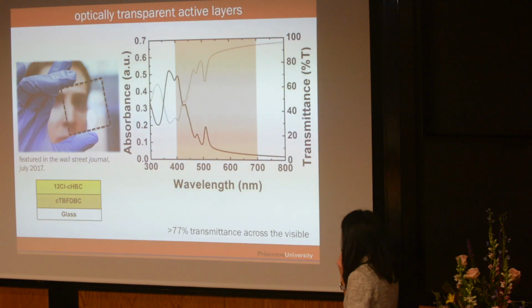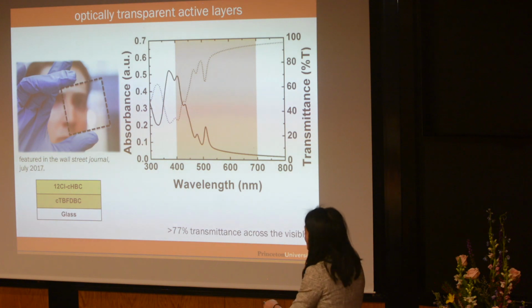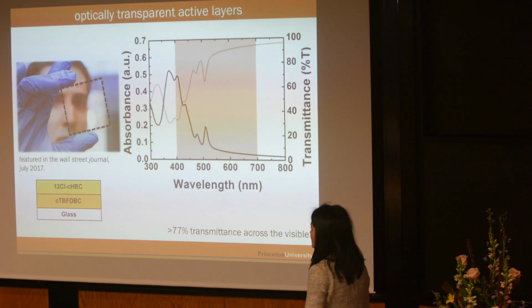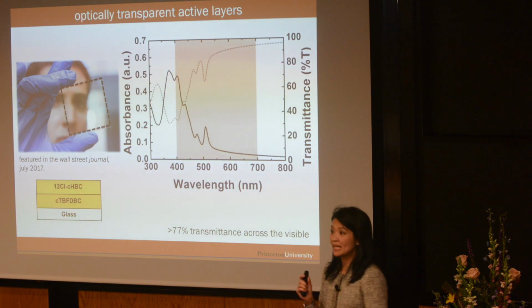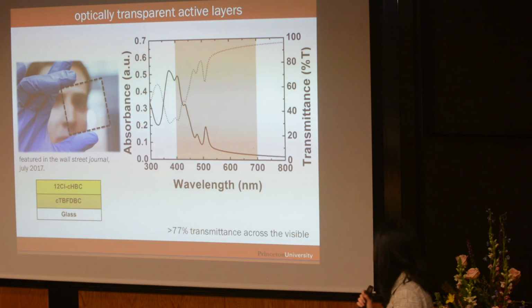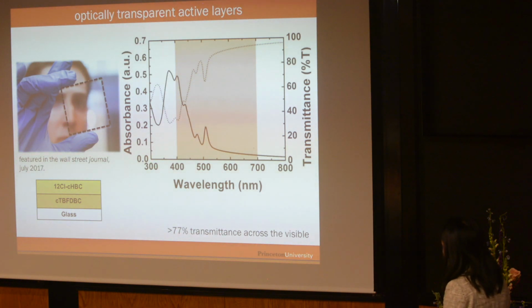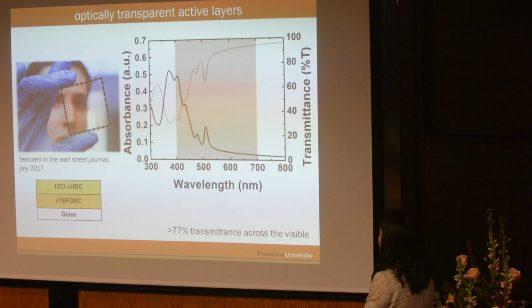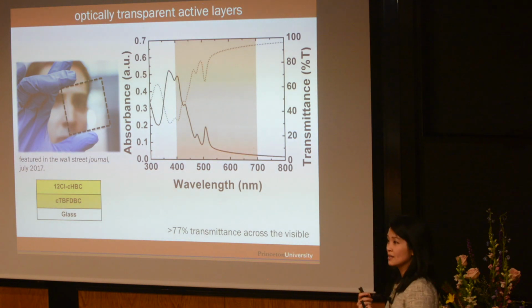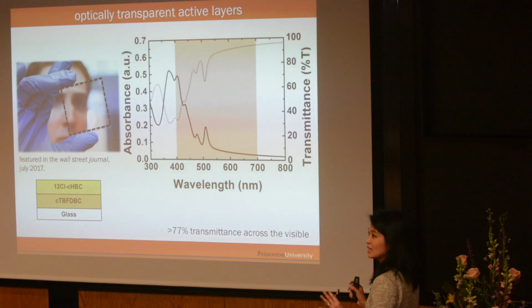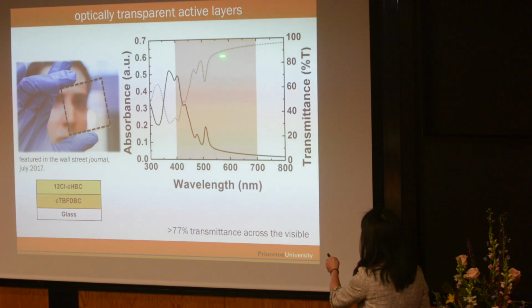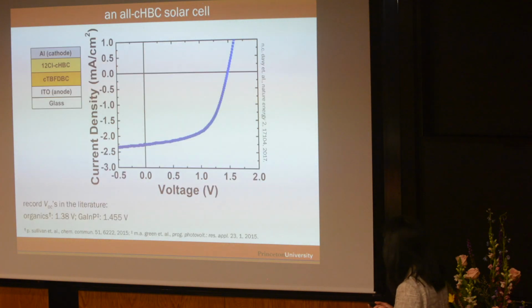So this is Nick Davey holding one of these films up. Again, TBF and 12Cl. These are only about 20 nanometers thick. So here I'm showing you absorbance and transmittance through the visible range, and you can see that it's over 77% transmittance across the visible. So much better, right, compared to C60. And so this is a transmittance curve. Does it work? The answer is yes.